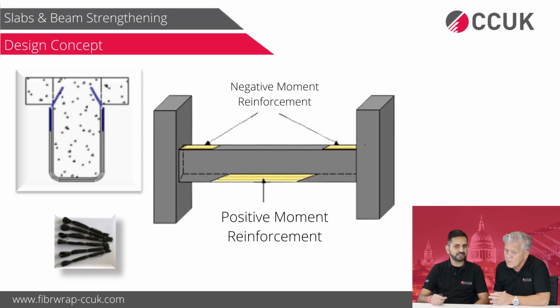So on our screen we can see a very simple schematic which shows where the carbon fibre is applied. Carbon fibre has very good properties in tension, so it is always recommended to be applied onto the tensile face of the structure. So in that image we can see that carbon fibre is applied at the underside in the mid-span.